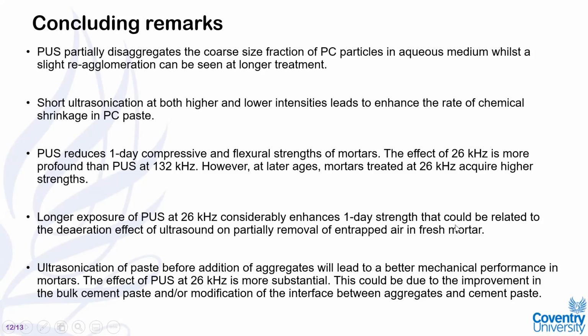This could be related to the deaeration effect of ultrasound on partial removal of entrapped air, the degassing effect of cavitation. And the last interesting result was related to the improvement in the flexural strength due to the sonication of paste before addition of aggregate to make mortar. We saw evidence of improvement in mechanical performance, which could be related to improvement or modification of the bulk cement paste property, or interfacial transition zone.